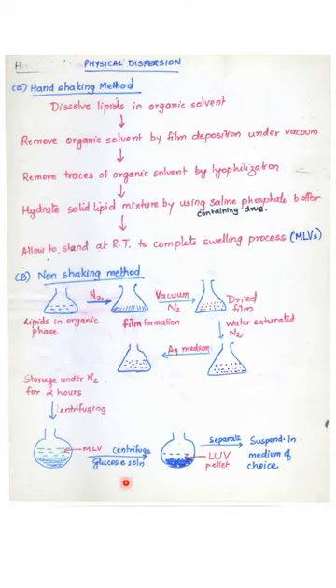The suspension is centrifuged at 1200 RPM for 10 minutes to get a layer of multilamellar vesicles which float on the top and the larger unilamellar vesicles at the bottom. So the multilamellar vesicles at the top, which are lighter, are removed, and the large unilamellar vesicles from the bottom, which form a pellet at the bottom, are then collected, isolated, washed and dried.